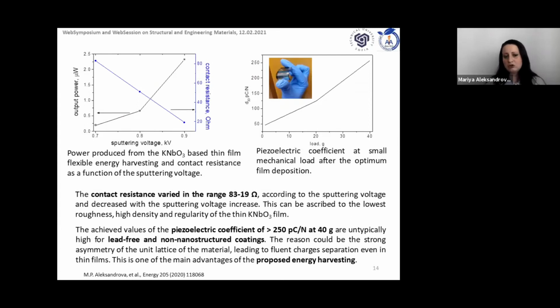And by controlling the deposition conditions, we succeeded to decrease the contact resistance to 19 ohms, which is favorable for the interface and contact conditions with the electrodes, helpful in addition to achieve a high piezoelectric coefficient greater than 250 picocoulombs per newton, which is actually untypically high for lead-free and non-nanostructured coatings. And this is the main advantage of the proposed energy harvesting.